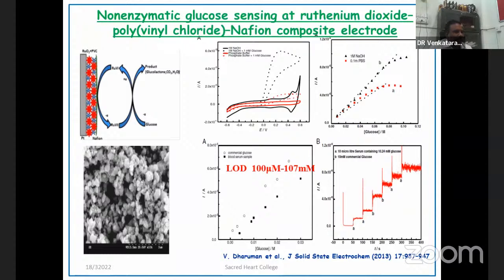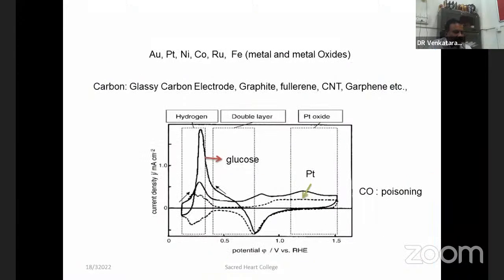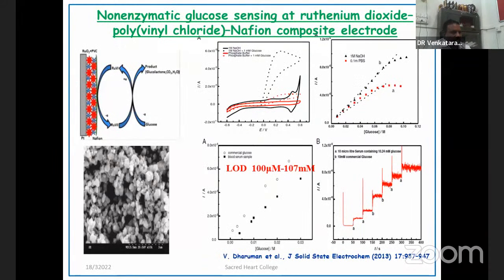And here we monitored glucose sensing in alkaline medium. Remember, your glucometer works with a blood sample, which has a physiological buffer of pH 7.4. But here, even in the previous slide, what I showed was platinum. Platinum, or metals and metal oxides in general, are very active in higher alkaline pH, greater than 10 to 11, so 10 to 12. This is the pH range where you can sense glucose or oxidize glucose effectively at the metal or metal oxide. So we investigated glucose sensing using sodium hydroxide, and also we wanted to extend it to the physiological buffer, so we prepared a phosphate buffer saline solution and tried to monitor the glucose sensing.